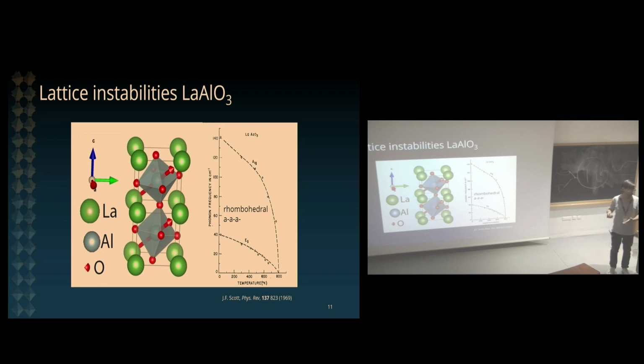Does this actually occur? Okay, so can we find experimental evidence that this idea is correct? So let's consider the case of lanthanum aluminate, a material with a very large band gap, above 5 electron volt, I believe, and so we are exciting it with laser pulses with photon energies of the order of 70 millielectron volt. Okay, so there's no electronic excitations happening here. So we are focusing on the lattice degrees of freedom.